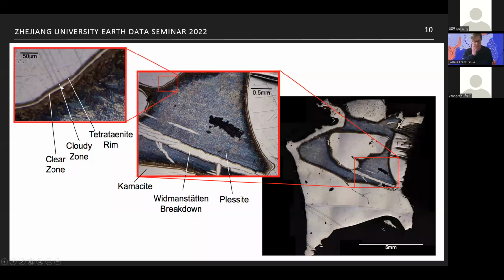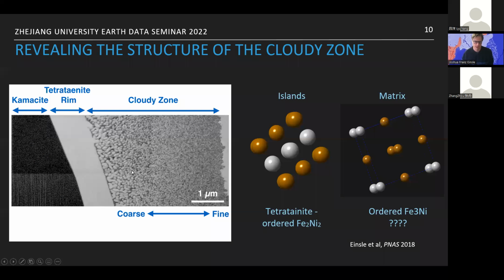The reason is that there was some very lovely work done by James Bryson in about 2014, where he'd shown that these small islands of tetrataenite, which is an ordered iron-nickel alloy in a 1-to-1 ratio, you can think of as alternating atomic planes of iron and nickel, works as a very strong permanent magnet. And so it could potentially record the planetary dynamo of what's going on.